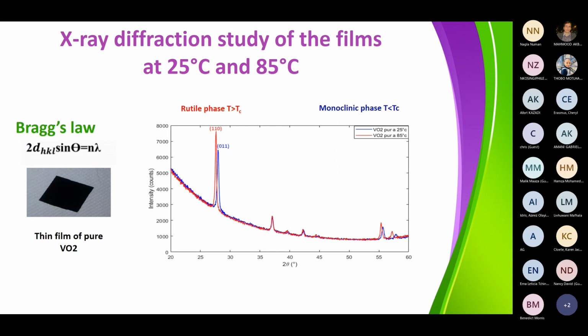So you make a film, and then you use X-ray diffraction in the normal way. That is to say, you are going to make a theta-2 theta experiment. You shine the X-ray beam at a theta angle. You put the detector at a 2 theta, and you measure the diffracted intensity as a function of the 2 theta angle. And you can do this in Le Mans. We have a diffractometer which is equipped with a nice cell, which is made with the Peltier system. And with the Peltier system, you can cool or you can heat the film very precisely with a precision of less than 0.1 of a degree Celsius. And so you can do the evolution as a function of temperature, like this.